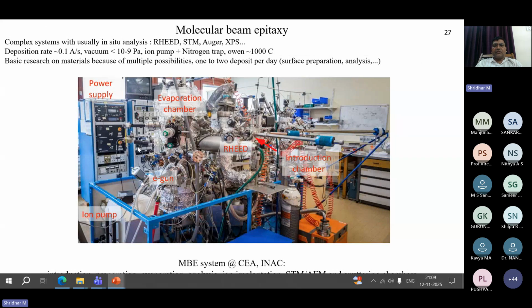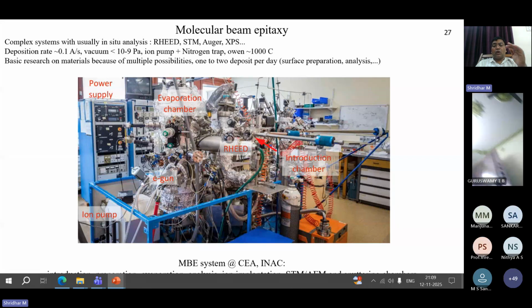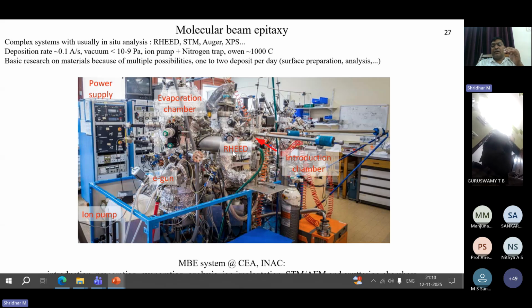In this area, this is the molecular beam epitaxy, this is the power supply, and this is the evaporation chamber. Suppose we want to deposit gold on silicon, so here you have to keep the gold, and this is the e-gun. The electron gun will help to melt the gold in the evaporation chamber. And this is the reflection high-energy electron diffraction introduction chamber. Whenever you want gold, you can open the gate. Whenever you don't want to deposit gold, you can easily close the gate. That you can do here.